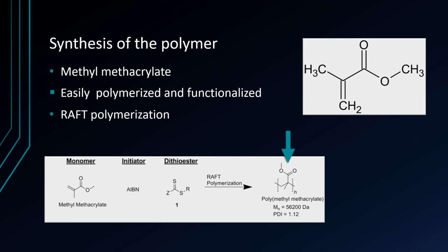The functionalization is done by changing the methyl group on the oxygen for something else more functional, like a benzene ring or a hydroxyl group. Changing to a hydroxyl group can be done by using palladium on carbon as a catalyst and hydrogen. The functionalization is important because this controls which functional groups are present in the molecule, and therefore the intramolecular interactions.